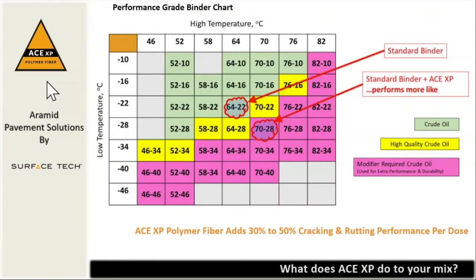One way to quantify the benefit of adding ACE-XP to your asphalt mix is to look at the performance in terms of a binder modification without actually using a polymer modified binder. ACE-XP will increase the rutting and cracking performance of the mix by 1 grade bump in the high and low temperature grades. So an asphalt mix made using PG 58-28 would be expected to perform like it was a mix made using PG 64-34.